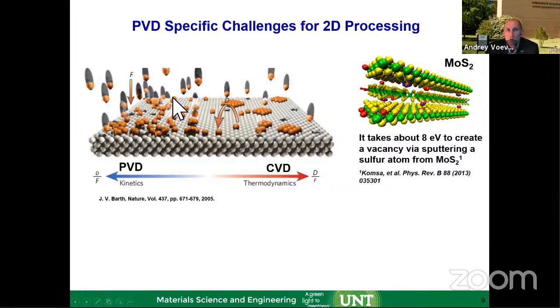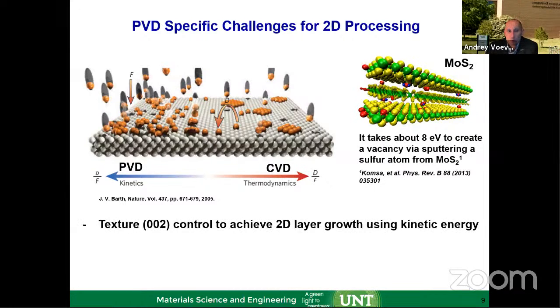One of the things you need to watch for in these processes with the kinetic energies is the formation of defects in crystal lattices. If we work with 2D molybdenum disulfide and want to fabricate it this way, using high energy to bring the atoms and form them, the atoms can also have enough energy to knock out the sulfur and create a sulfur vacancy, and a vacancy in the presence of oxygen can be filled with oxygen. So you can create vacancy defects or oxygen incorporation. So you need to watch out. It takes about 8 eV of energy to create a vacancy.